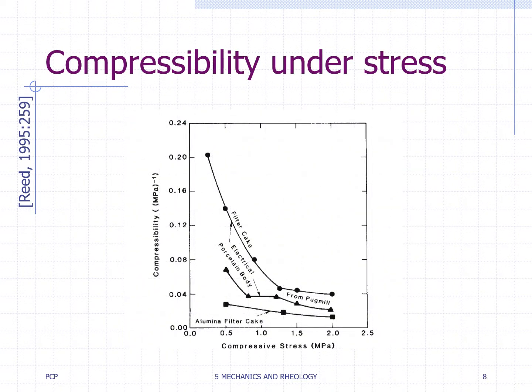A uniaxial press filter cake of a flocculated electrical porcelain body is shown in this figure. The primary compression of filter cake, up to about 1 megapascal, is typical of the collapse of the coagulated clay coating hard particles, which reduces the spaces between particles. Above 1 megapascal, the behavior is typical of clay with a more oriented structure.